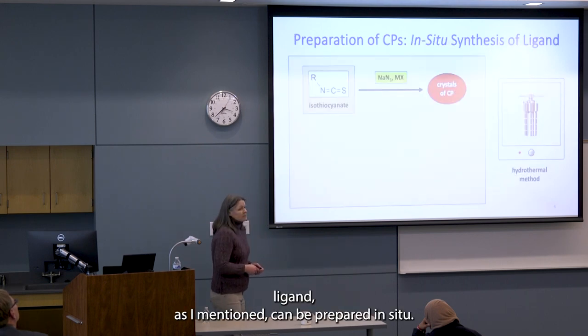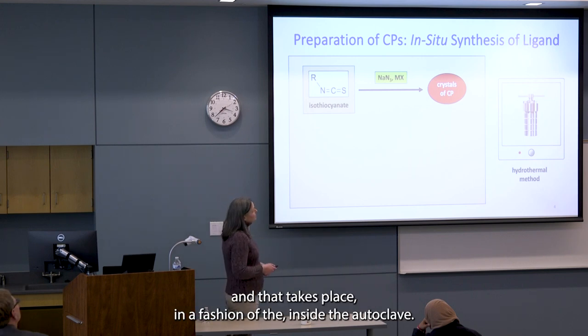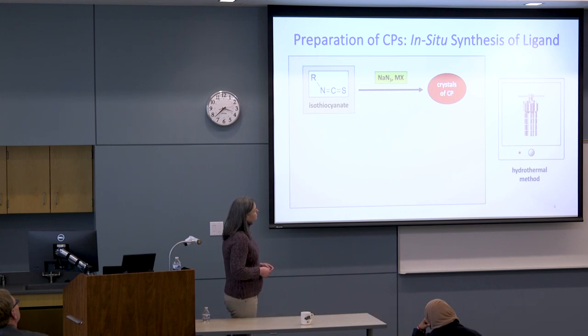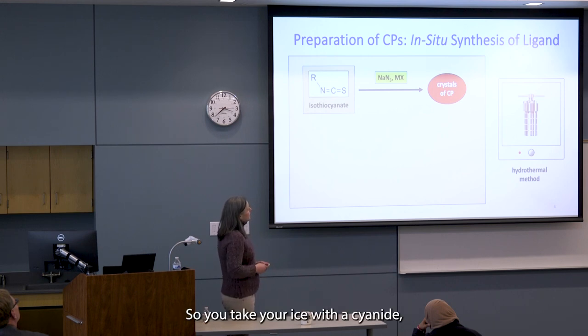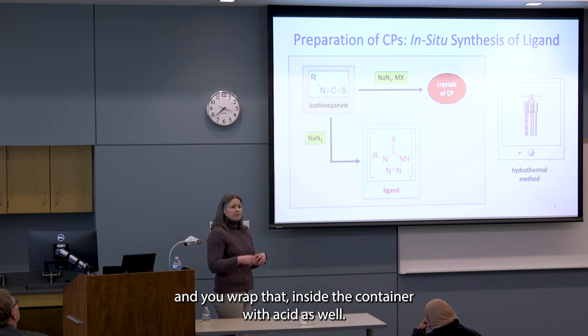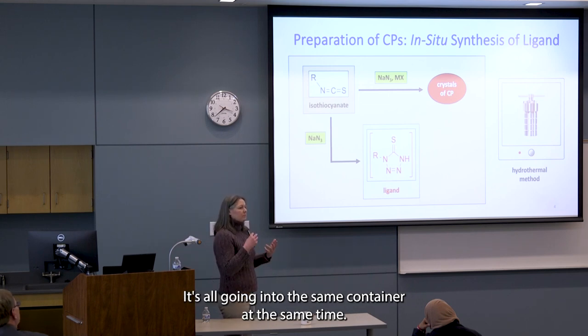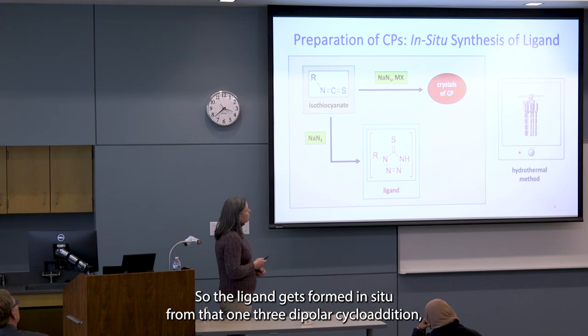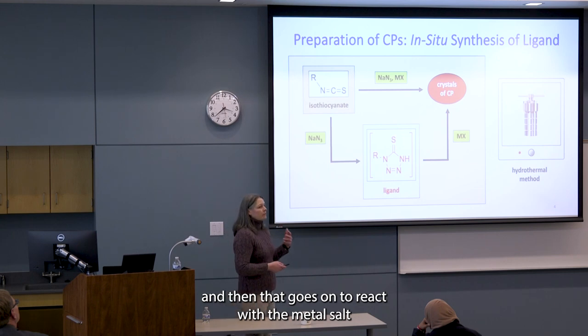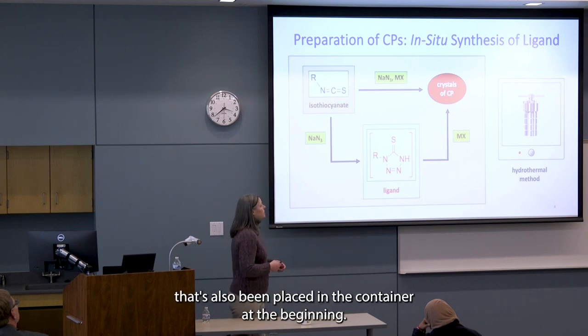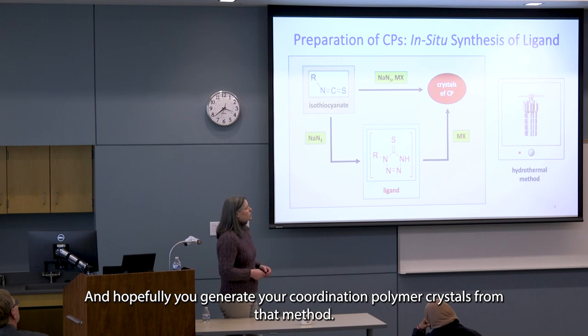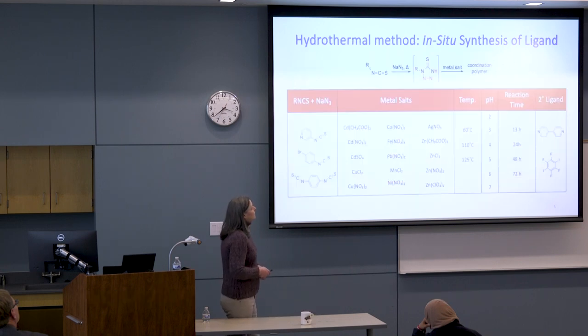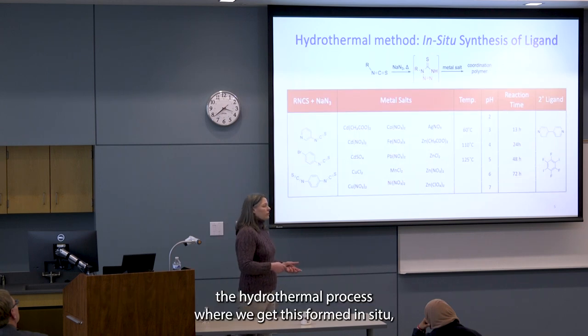So the ligand, as I mentioned, can be prepared in situ, and that takes place inside the autoclave. So you take your isothiocyanate and you react that inside the container with azide as well. It's all going into the same container at the same time. So the ligand gets formed in situ from that 1,3 dipolar cycloaddition, and then that goes on to react with the metal salt that's also been placed in the container at the beginning, and hopefully you generate your coordination polymer crystals from that method.